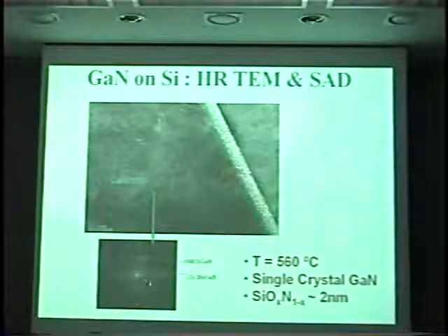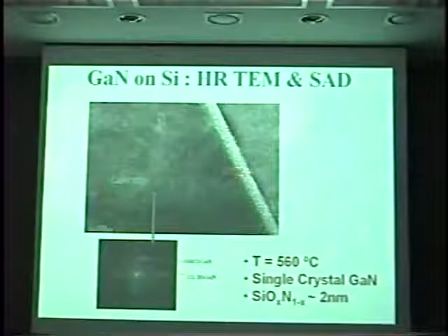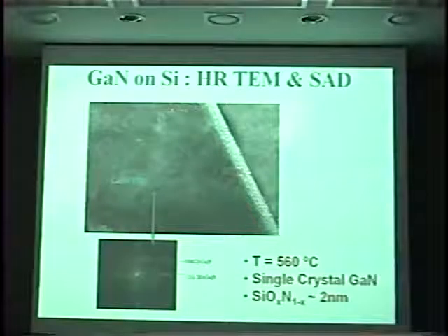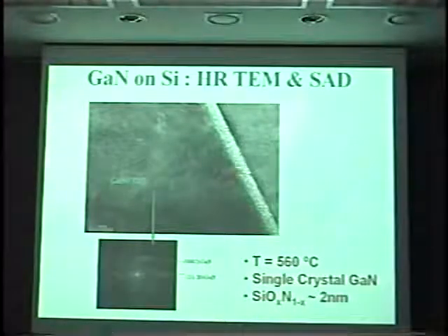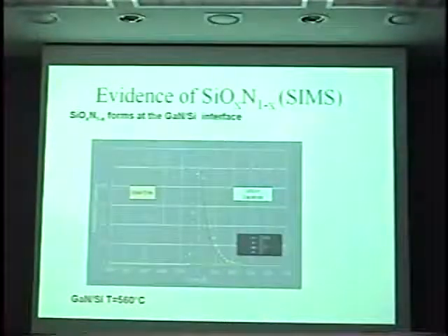The selected area diffraction pattern shows that indeed it is single crystal, and we follow through fairly well with a lattice match to the underlying silicon. There is this compliant layer that forms during the process. What we believe is going on is, even though we have a clean silicon interface to begin with, there is dissolved oxygen in the silicon, or perhaps we do have a little oxygen coming off the walls, but we form this silicon oxynitride compliant interface. If we look at the SIMS analysis or profile across that interface, we see both silicon, oxygen, and nitrogen at that interface.